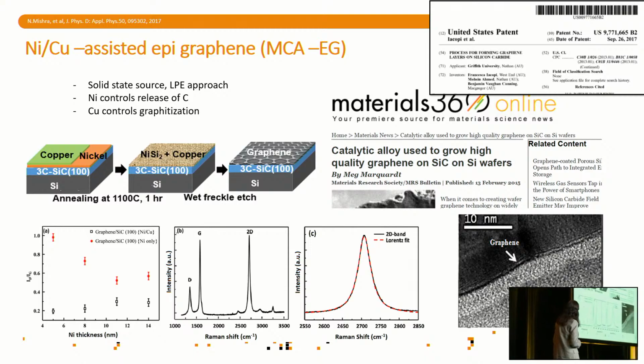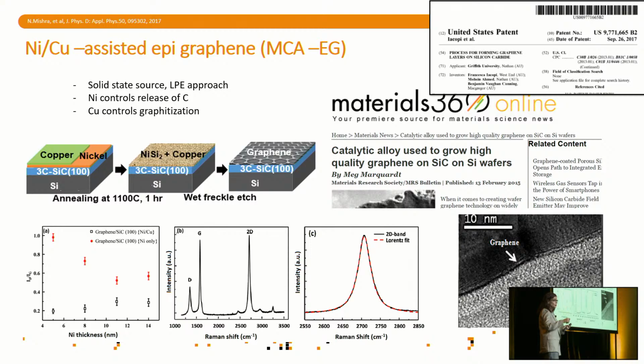We thought, okay, how about alloying the catalyst with another catalyst so that we have two knobs? And that works beautifully, because by combining nickel and copper, which alloy very well, we have one knob, the nickel, to release. With the nickel, we control how much carbon we release from the silicon carbide underneath. And with the copper, we control the graphitization. Not only that, but there is an effect that is just as important: we do all of that at 1100 degrees, so much lower than the 1400, 1500 and such. But at that temperature, copper and the silicides are in liquid form. So that's beautiful, because in that case, you're doing a sort of liquid phase epitaxial growth.